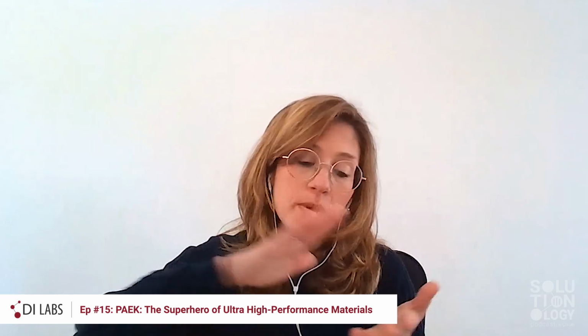So with LM PAEK, we changed the crystallization speed. It crystallizes much more slowly than PEEK. This basically allows you to widen your processing window in filament fusion. The polymer will not crystallize as fast, so it will be able to be deposited a bit more easily. The part will not move or distort. But these characteristics also allow better diffusion of the polymer chains between layers, which ultimately impacts the interlayer adhesion and the strength of your parts.